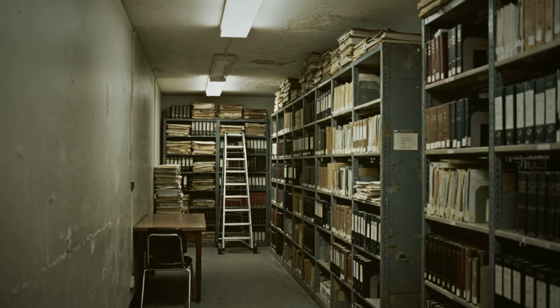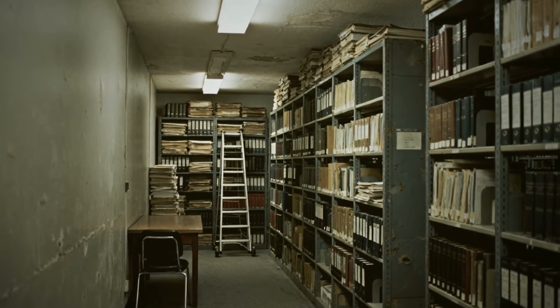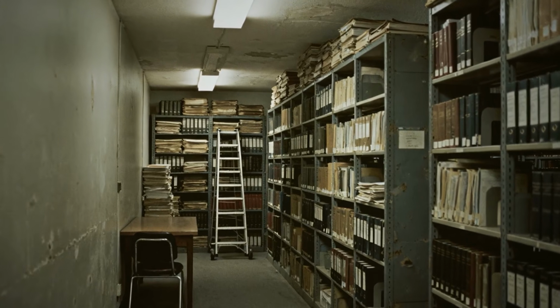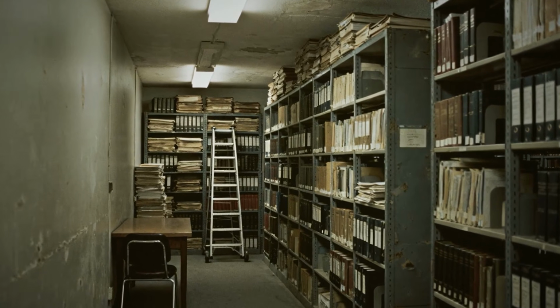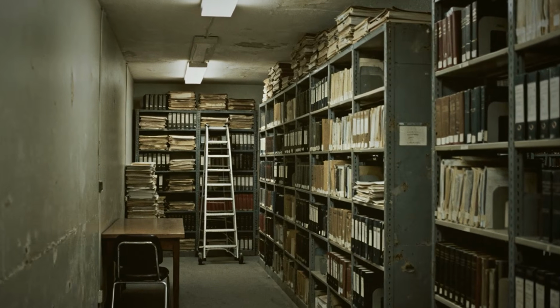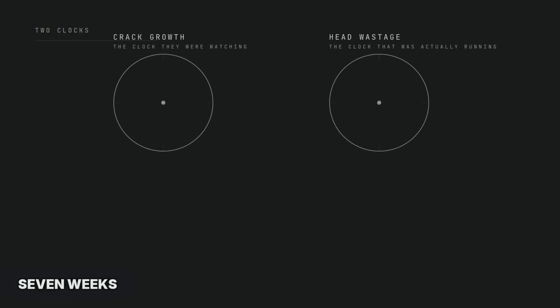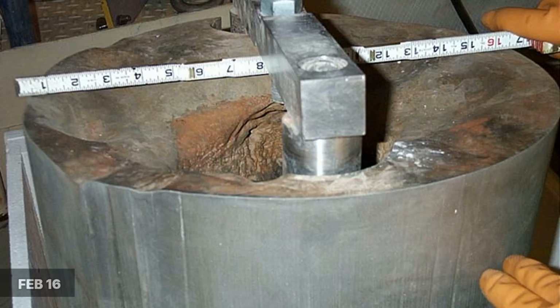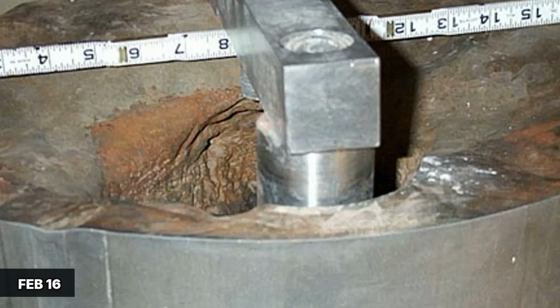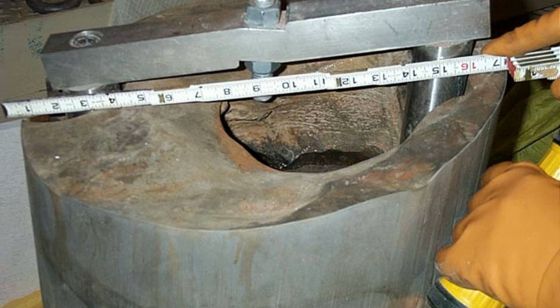The regulator later found its own analysis had not anticipated how severe the corrosion risk from a leaking nozzle could get. That is the failure in one line. The people arguing about the schedule were arguing about crack growth in a tube. The thing actually running was the destruction of the vessel head around the tube. They were watching the wrong clock, and they moved the deadline on the clock they were watching by 7 weeks.